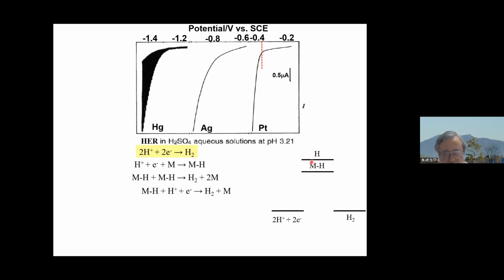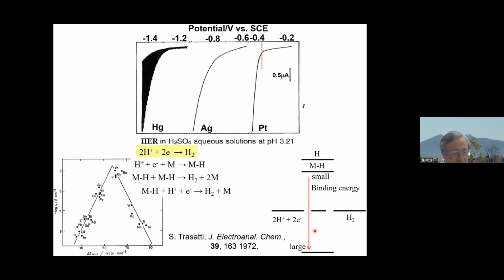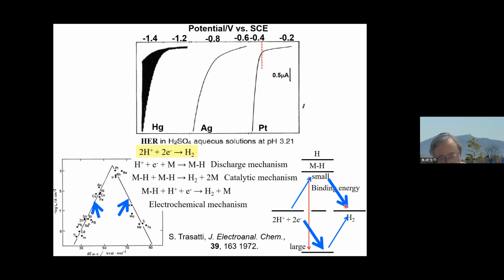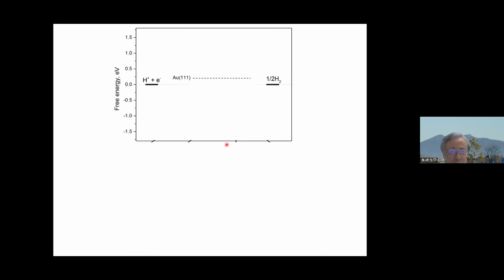Energetically it looks like this. The first step, if it is in vacuum, goes very high, but by adsorbing on the metal, depending on the adsorption energy of hydrogen, the intermediate state changes from here to here. If you plot the rate of the hydrogen evolution reaction as a function of the metal-hydrogen bond, it looks like this. It's called the famous volcano plot. In this region, increasing the adsorption energy means decreasing this height, so the higher this energy, the higher the rate, because it's going down. But if it goes down too much, then it becomes harder for the second step. So it goes like that. This is a famous plot. Then we also calculated this for the boron nitride case.